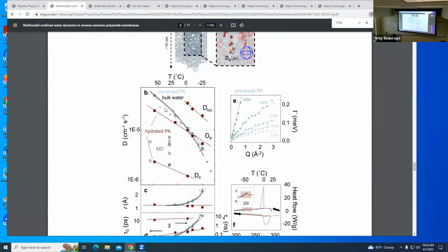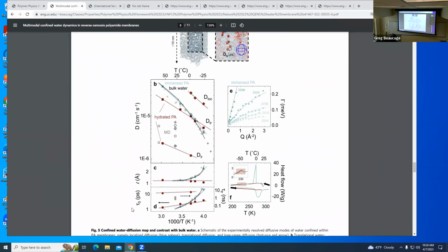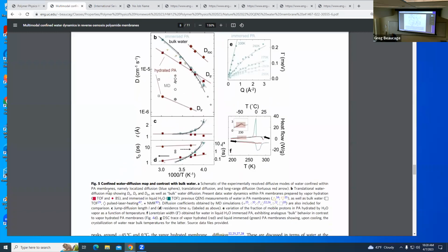In the end, he measures the diffusion, this popping time, so the time it resides and then pops, like this DTR thing. So that's the tau. And he has two instruments. He's got a BS instrument, which is kind of an odd acronym. That's the backscatter, which is at long times. And then he's got a time of flight instrument, which is at shorter times. So he's got two taus here. This is picoseconds, I think that's the TOF, and the backscatter is nanoseconds, right? So the two machines are on two different time scales. They both seem to work the same way.